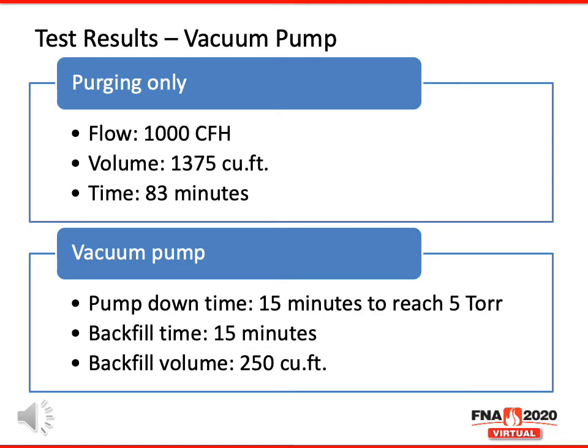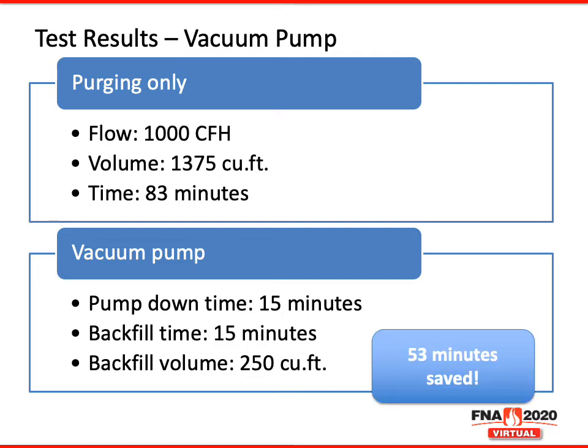If we look at using a vacuum pump to achieve a similar purge step, the vacuum pump used is a 15-minute time to reach a vacuum level of 5 torr. Then there's a nitrogen backfill that has to occur in order to repressurize the retort prior to proceeding on the cycle, and that's about a 15-minute time as well. And the total gas used during this time was 250 cubic feet. So in all, there's a 53-minute savings by replacing just a purge-only step to instead using a vacuum pump with a nitrogen backfill afterward.